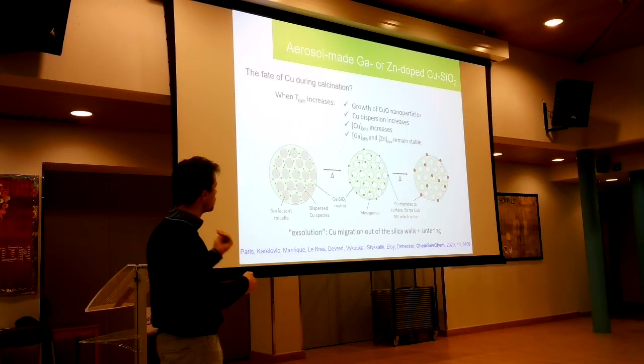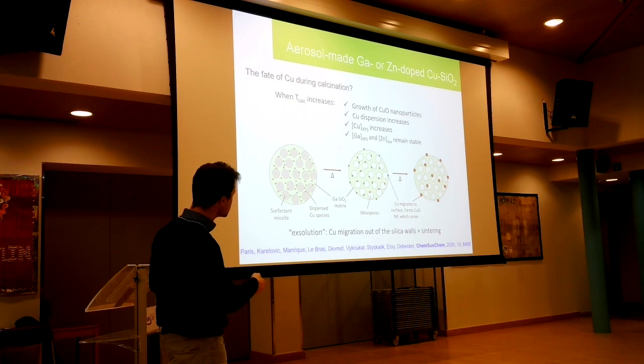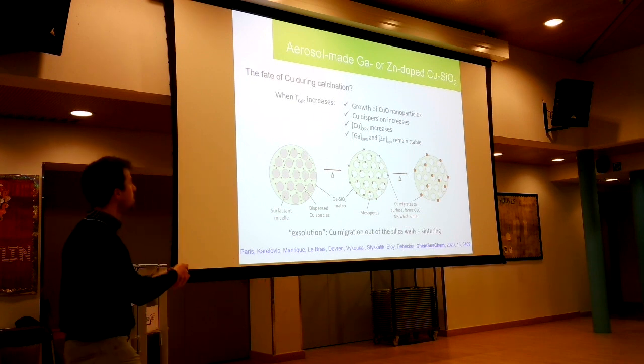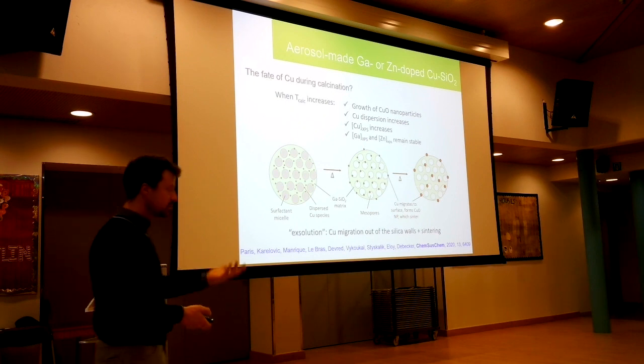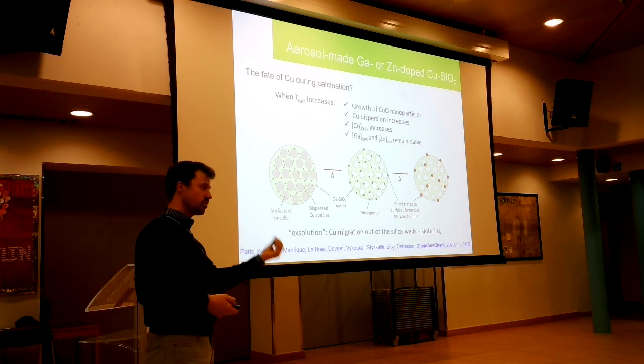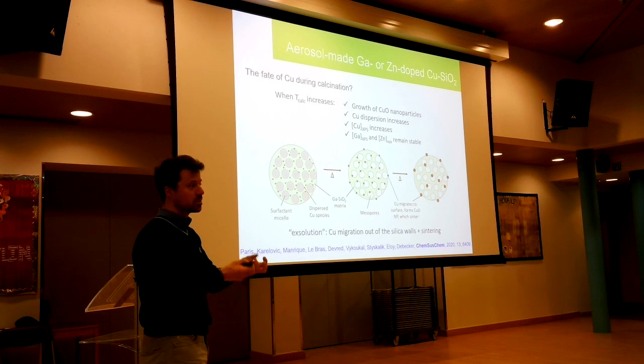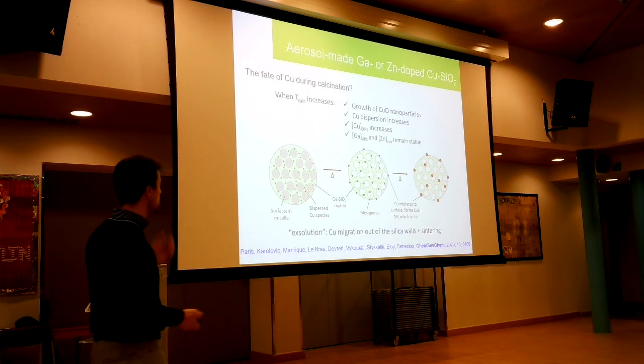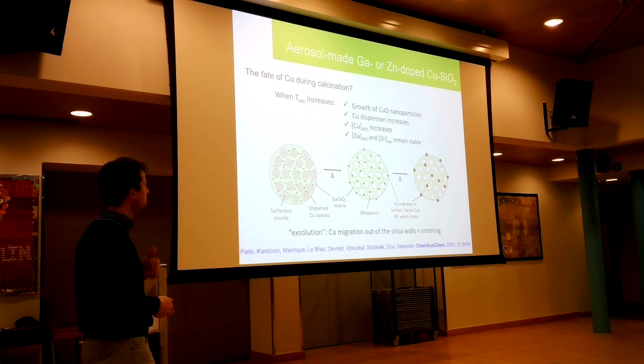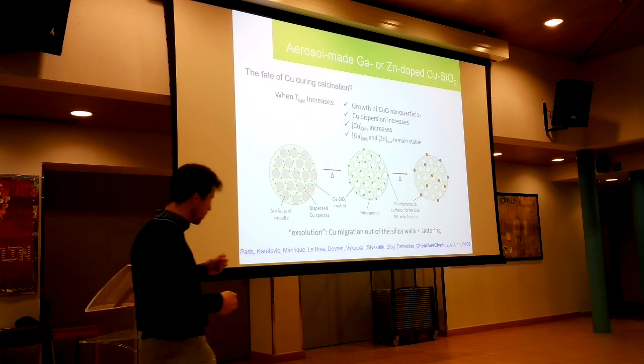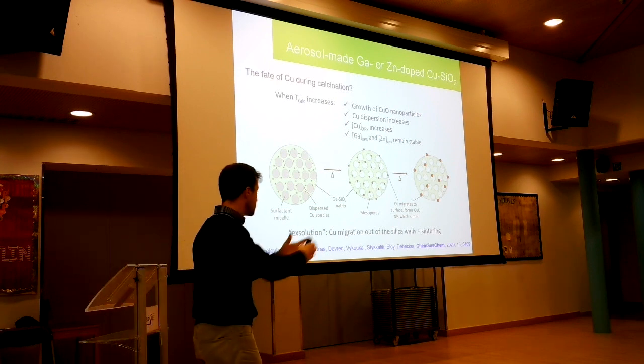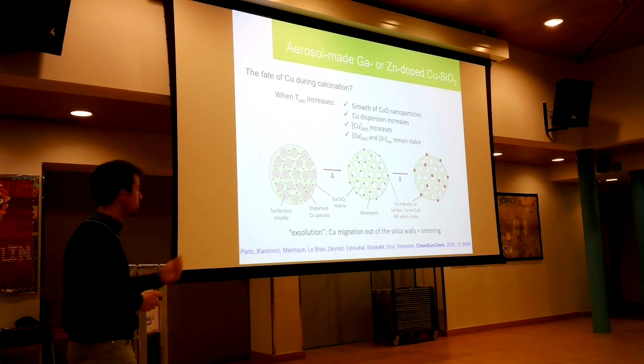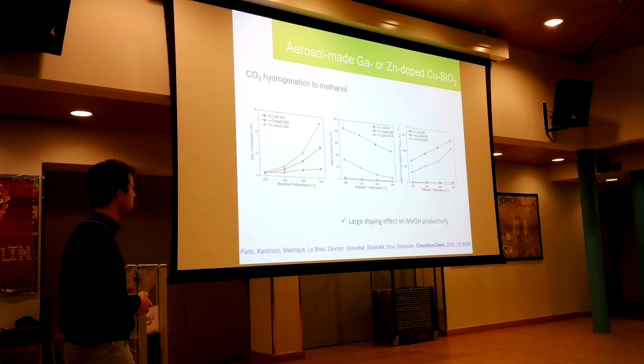If you go too far, if you heat up too far, you will again aggregate or sinter those small particles and form bigger particles. So of course there's a kind of optimum that you have to find to form the porosity, to form the copper nanoparticles, but not too big, right? So that's what we did. And this process is called exsolution of the copper. So the copper is in the material, but then when you heat it up, it tends to go out, and you can control this to a certain extent.